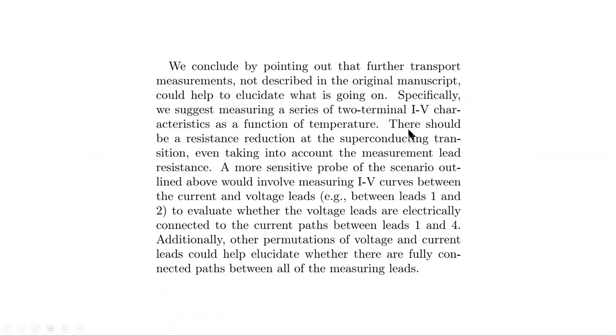So we suggested that IV curves be shown or measured, and that if you looked carefully at these IV curves, you would be able to tell, for example, that all of the leads are connected and everything is ohmic before it goes superconducting or even after it goes superconducting, to make sure that you're really measuring what you think you're measuring. So we had some constructive suggestions.